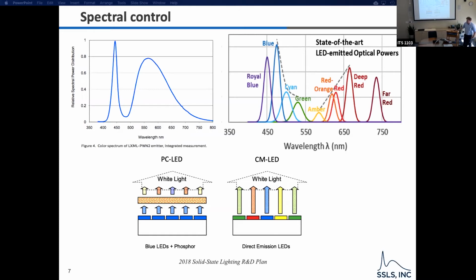Right now, the blue LED materials are semiconductors grown in what we call a metal organic chemical vapor deposition reactor, grown at 1200 plus degrees C, with almost atomic layer control over the thickness while you're putting in alloys and various impurities to get the semiconductor just right. It is really a marvel how good these things are. And so with the blue LED right now, for every electron that goes into the light generating layer, it's 90+% efficient. So 100 electrons go in, 90 plus photons come out.